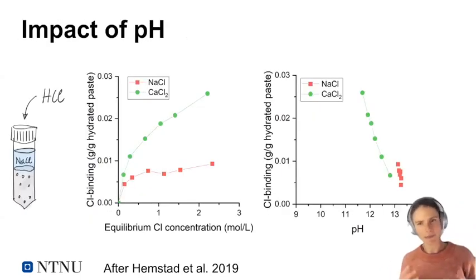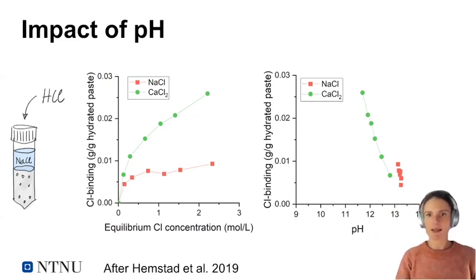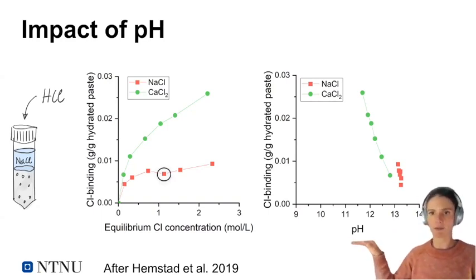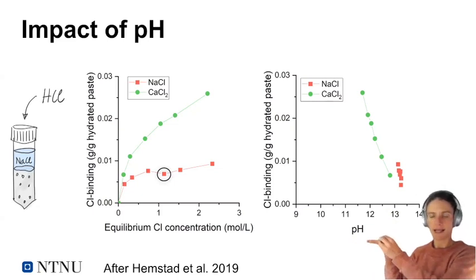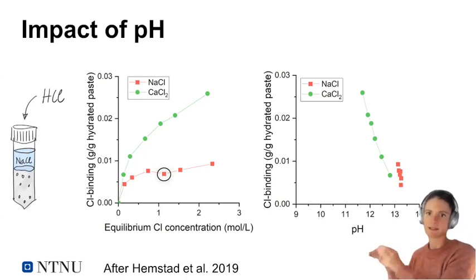So in order to dig a little bit deeper into this pH dependency, we did another setup. We repeated the binding isotherms, and then we said, let's take a point on the sodium chloride binding isotherm, which is actually on a plateau, and let's add hydrochloric acid. The things we're doing then is we're adding more chloride, so we're moving further along the horizontal axis, and we are changing the pH. We're not adding any other elements, we're changing pH and adding more chlorides.